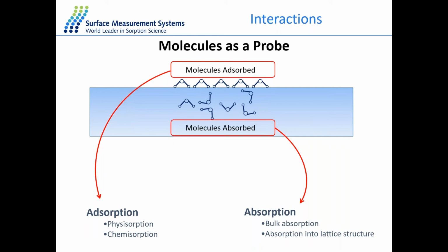In this case, we can determine the vapor-induced phase change, where we can get the glass transition humidity from the set of data. The last kind of interaction is the absorption into the lattice structure, which means the sample will change its structure in the presence of water or organic vapor, and this will lead to the formation of a hydrate or solvate. So by the DVS technique, we can characterize all these different properties of the solid material during storage or processing, and the parameters we get from the DVS data are closer to the ones we use in real applications as well.